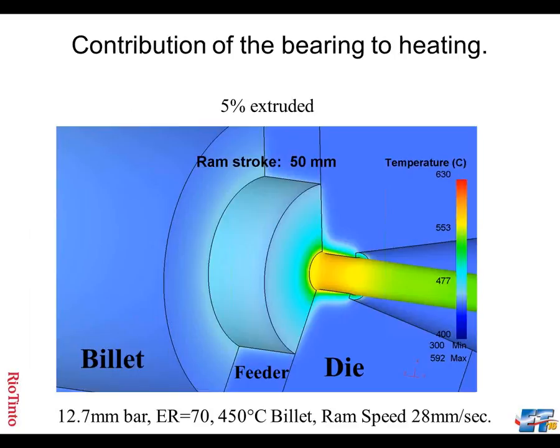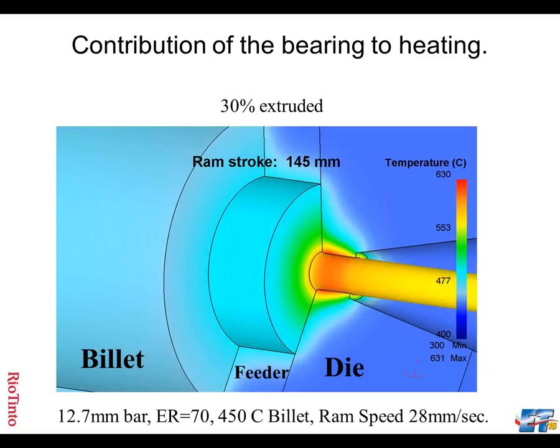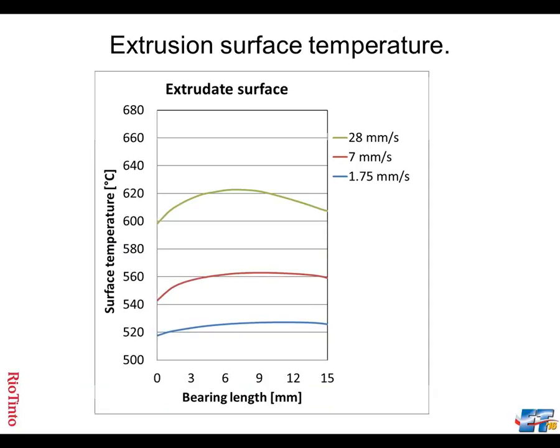And I'll just show you a couple of illustrations of the kind of thing we can model. This is 5% of this material extruded. This is 30%, 80%. You can see that the temperature is extremely local. The material, after leaving the die, has a uniform temperature within a fraction of a second, long before the metal's left the bolster. We're never going to be able to measure this. That's why we think modeling is so useful.